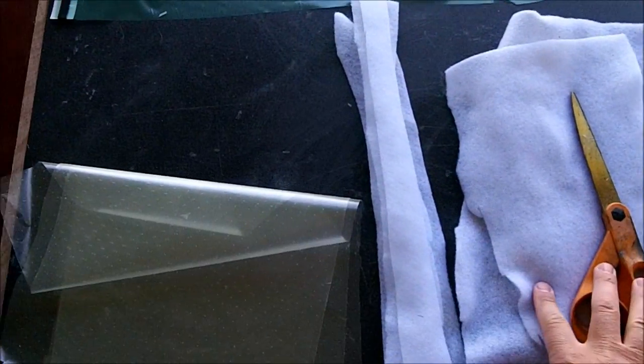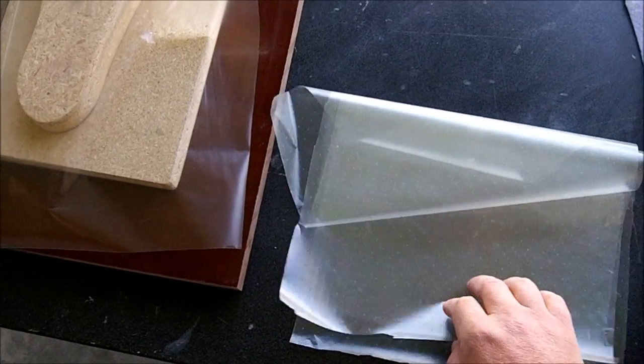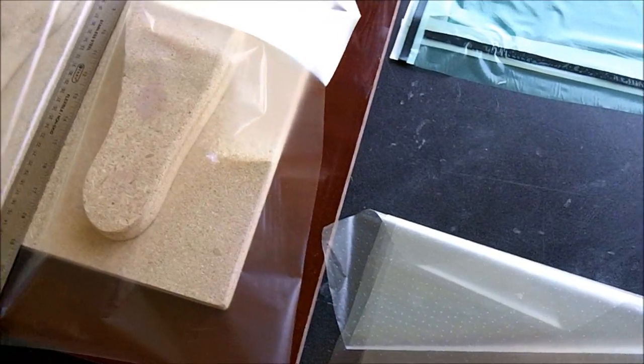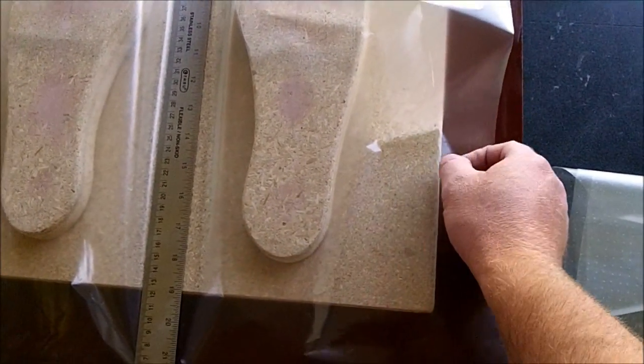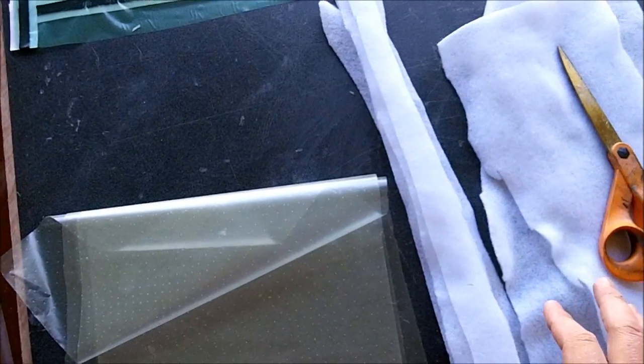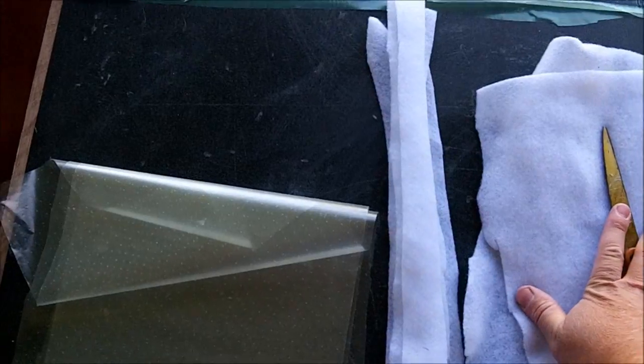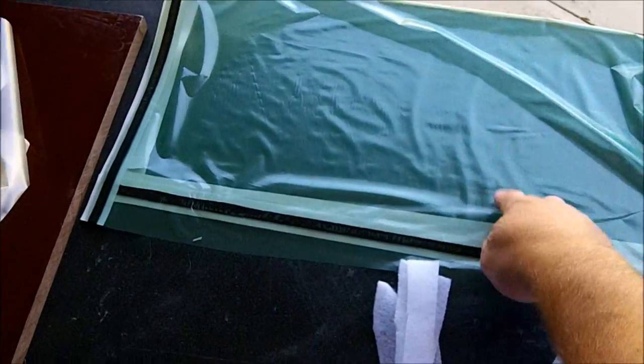I've also got my breather ready to go. I'm going to be using perforated plastic on top of the carbon fiber. Just to give you an idea, it's going to go this plastic, carbon fiber, perforated plastic. I'm not going to be using any peel ply on this. And then, I'm going to be using breather on top of that. And then, the Stretchlon.